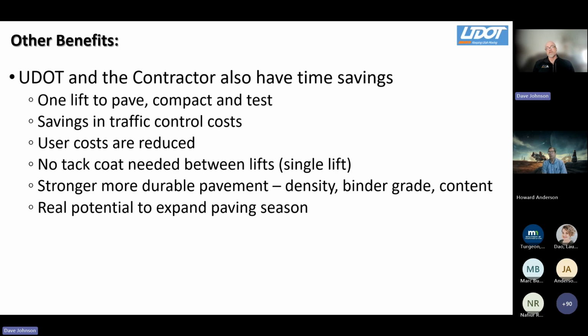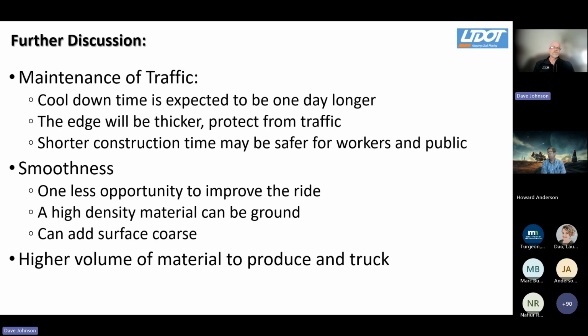We really also, as I mentioned before, see a potential of expanding the paving season, both early, maybe not quite like we have today in Montana at 0 degrees Fahrenheit, but early season and late season paving windows can be expanded because of thick lift paving and the cooling rates that are extended under those designs. Maintenance of traffic, it does take longer for this to cool off, and especially where you have heavy truck traffic, that should be considered in when you choose to reopen this material.